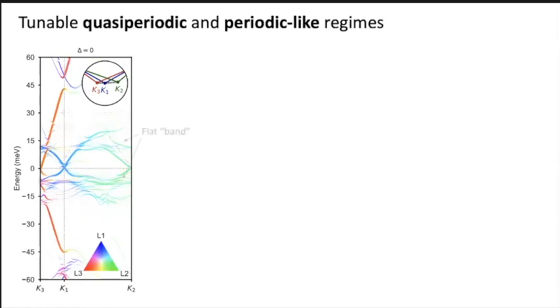Then you have these other regions where you have a spaghetti of flat bands. There is where the quasicrystallinity is manifest and the electrons will see it. In addition, at higher energies, you have a fast band which retains its character because it's a little bit more decoupled, because one of the angles is a bit larger than the other. So in this region, the electrons are going to think they're in a periodic system. In this region, the electrons are going to see that they're in a quasi-periodic system.